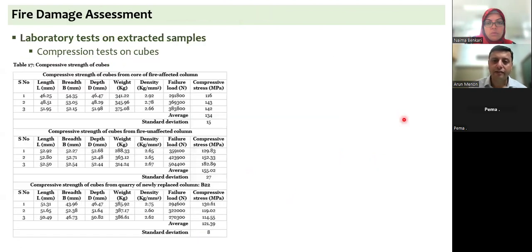So we went ahead, we did testing of some columns that had collapsed. So we could take samples from them. We took samples from different parts of such affected members, and we did compression tests in the laboratory. And we realized that, strictly speaking, the compressive strength of this granite was not lost in some of these columns. If we were to take a column that was very badly affected by fire, but take the core of the stone and check the compressive strength of the stone, it was really not compromised.